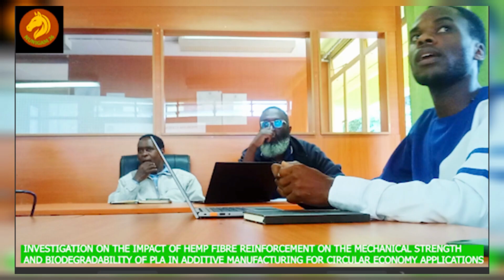About treatment, the purpose of treatment is to modify the surface so that it can be rough, and when something is rough, it is very easy to bond. We use sodium hydroxide for 30 minutes to 3 hours, concentration of 6% at room temperature. After alkali treatment, we shall do washing so that we can remove chemical substances and dirt. Then we dry.